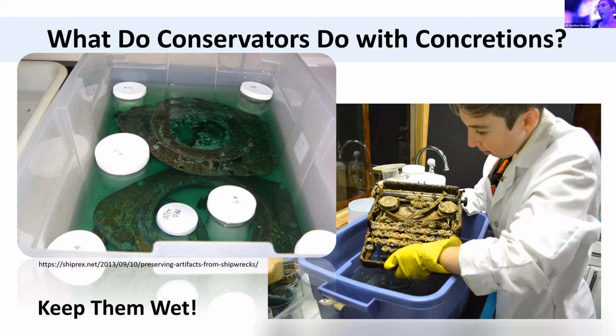And kind of the rapid change from a wet environment to a dry environment can be very challenging for a lot of artifacts. It can cause a lot of problems, one of which, because it is in a saltwater environment, if we're excavating from the ocean, for example, that salt is actually inside the artifact by this point. You can imagine if you have salts inside your artifact and it's okay when it's wet because it's in solution, all of a sudden you're drying it out, that salt precipitates out of solution, it recrystallizes and it's growing. Except it's growing inside your artifact.